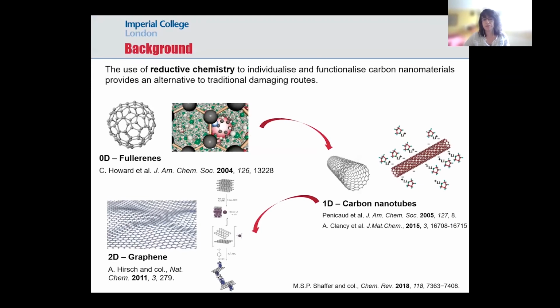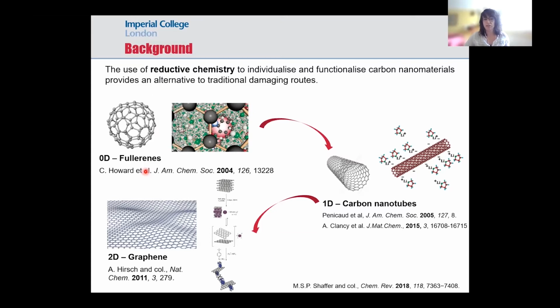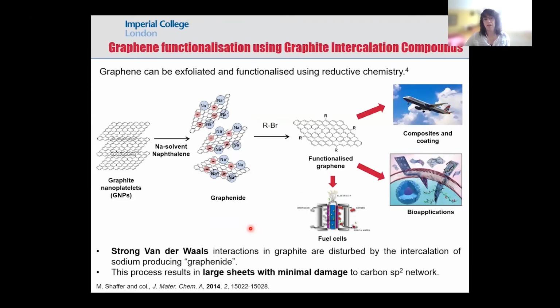There are different techniques to treat nanomaterials and make them more compatible with solvents in order to use them in different applications. One of these techniques is reductive chemistry, to individualize nanomaterials and improve the processing. So we move from, I'll put the pointer, zero-dimensional materials such as fullerenes. They have been charged using potassium in ammonia, then move to one-dimensional materials such as carbon nanotubes, and eventually we move onto 2D materials such as graphene, which is the topic I'm going to explore here. So in our work, we use a mixture of sodium and naphthalene and a specific solvent, either THF or dimethylacetamide.